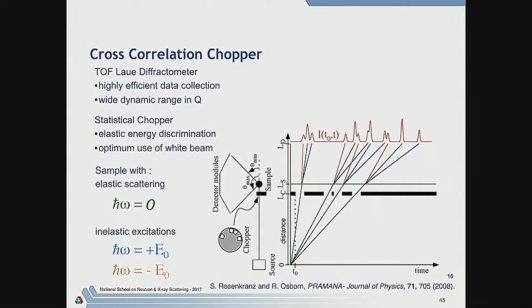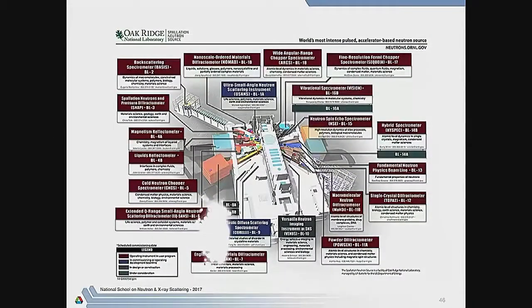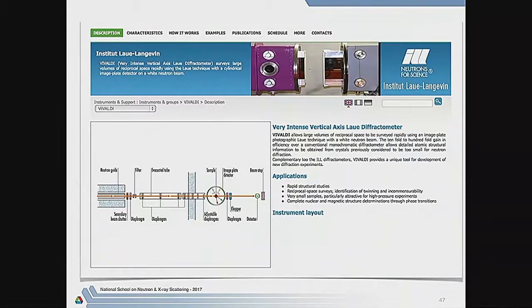However, this is not very much use because everything's scrambled. We've got elastic peaks and inelastic peaks all appearing in the same time channels. How do we unscramble them? And that's where the mathematics becomes interesting, because if you actually cross-correlate this signal with the pseudo-random sequence that you use to modulate the beam, miraculously you get out the original scattering as a function of energy transfer. Cross-correlation gives you essentially the three-peak structure back again. So this machine, Corelli, is actually being built on this beamline here, and it's been running for about 2 years now.